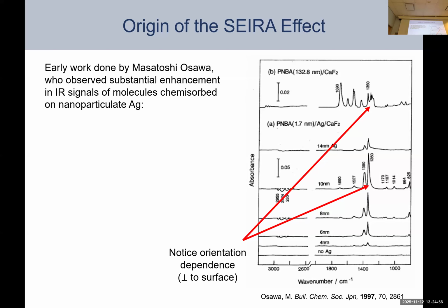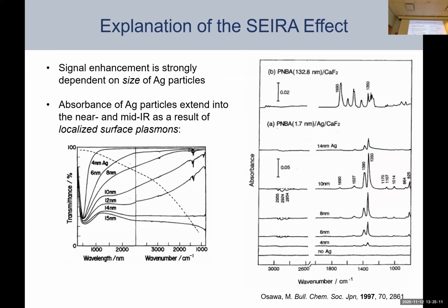And so that's telling us that there's an orientation specificity for this molecule when it binds to the surface. So we can actually get quite detailed information here if you understand your system well enough and you know what you're looking for. Okay, now why does this happen?